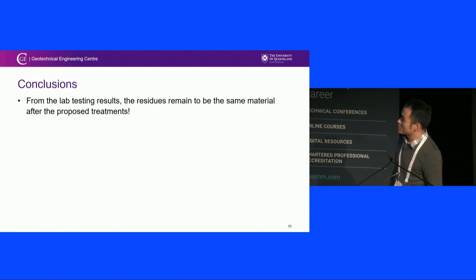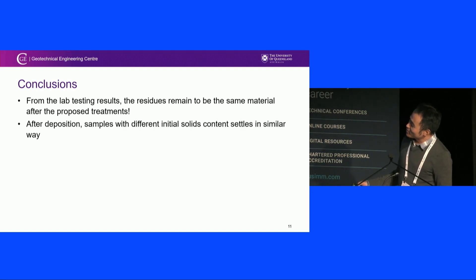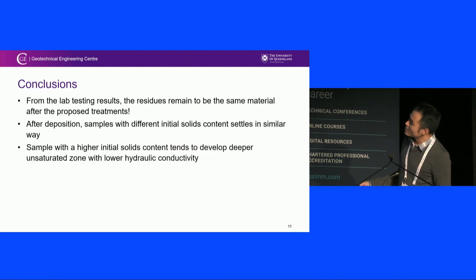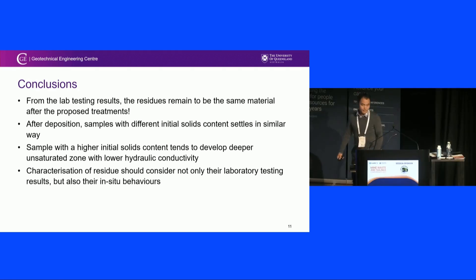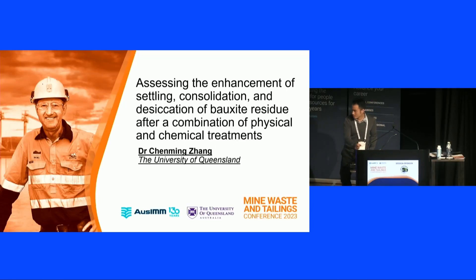A list of the conclusions. From the lab testing, the residue remains to be the same material after proposed treatment, unfortunately. After deposition, samples with different initial solid content settle in a very similar way. This has also been confirmed. Sample with a higher initial solid content tends to develop deeper unsaturated zone with lower hydraulic conductivity. And the final thing is, this is very critical, the characterization of the residue should consider not only their laboratory testing result, but also their in situ behavior. Thank you very much.